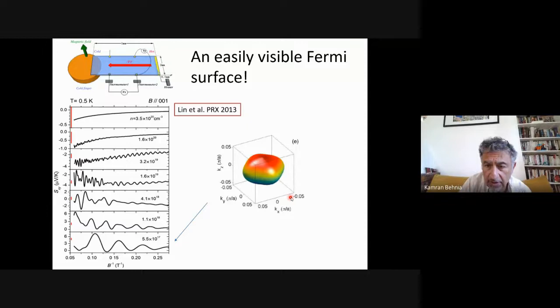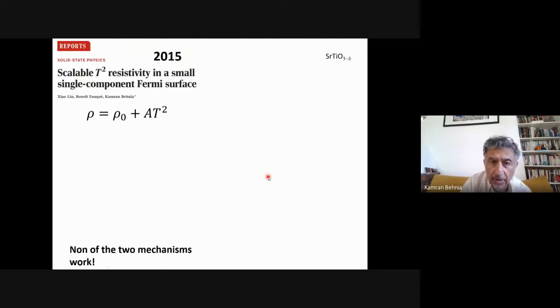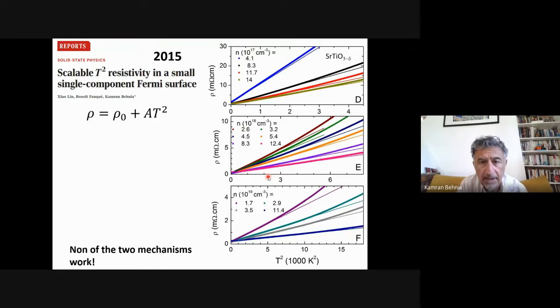So here, in units of the reciprocal lattice, is basically a small squeezed ellipsoid, as was predicted by band structure calculations. Now, for the sake of this talk, what is interesting is that you can see clearly T-square behavior. You can actually look at how this T-square behavior evolves when the system is extremely dilute, 4.1 × 10^17.